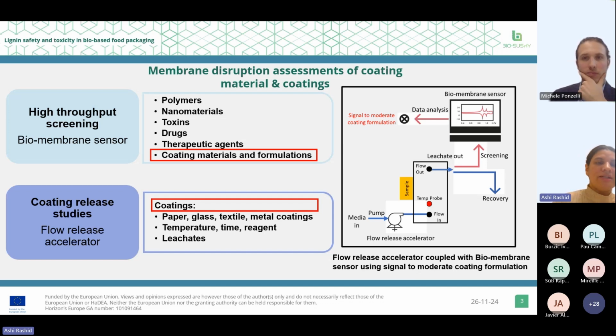In the second step, release studies are performed on the coatings using the flow release accelerator. And during the release studies, these coatings are exposed to the reagents under different conditions of temperature, pH, and reagent composition, simulating the natural environment.